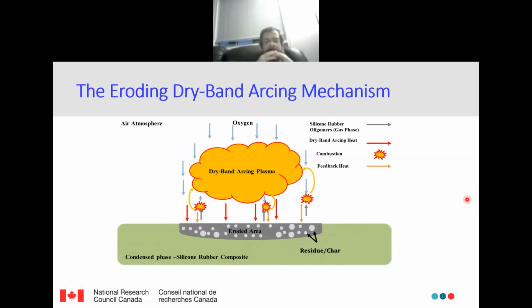Now, this is another illustration to show how the environment, the surface, and the pollutant can all have a synergistic effect to damage the surface of the material. Here we have the silicone rubber material, and when you have dry bands, you start to have dry band arcing. So you have arcing in the presence of oxygen on the surface. We have a plasma, because the arcing has a very high temperature that can reach hundreds of degrees centigrade. This will cause some erosion, some char on the surface of the material.